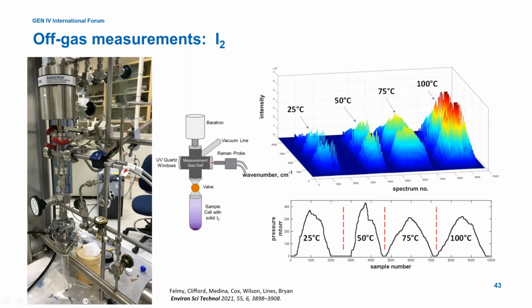The picture shown on the left-hand side is very busy and very hard to see, so it's easier to see with the diagram here. We have our iodine capsule, our metering valve, a Raman probe and our gas manifold measurement cell, and a Baratron gauge, and this is on a high vacuum line. So we can easily measure the pressure as a function of temperature throughout this, and we have beautiful fluorescence spectra at variable temperature and pressure.